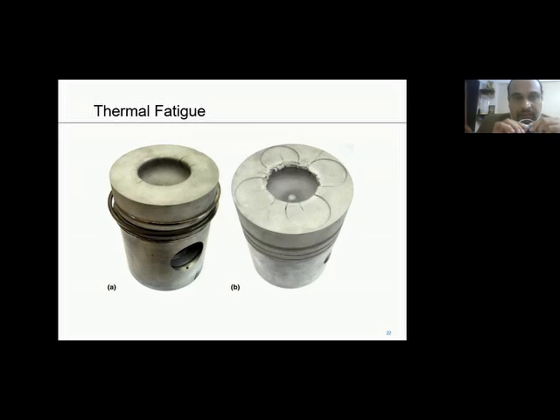The slide here talks about thermal fatigue, typically observed in pistons of the engines. You can see in the first picture there are cracks happening on the crown of the piston, a couple of cracks, or 2-3 cracks here. And the second picture shows the severity of this thermal cracking. Why this happens is because the piston top is subjected to repetitive heating and cooling due to the combustion. So it is subjected to thermal stresses. That's why the micro cracks generate, and then they eventually lead to failure of the piston. In addition, you can see the valve stamping also on this piston. The reasons are different, but the basic point here is that there are thermal cracks, so something has gone wrong in terms of the temperature in the engine, the combustion temperature.